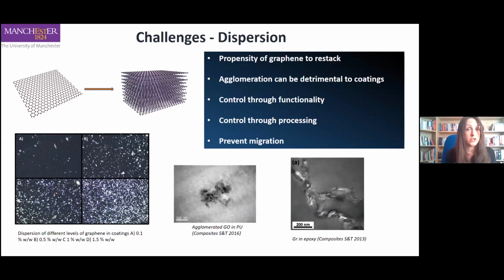So milling, high shear, dispersion, maybe the use of rheology modifiers to keep that graphene dispersed while your coating is curing. There's so many things you have to think about. The other thing you can do is to functionalize the graphene, and that can help with dispersion, especially if you're in sort of an organic polymer matrix. GO, for example, has all those oxygen groups and can help dispersion, and those functionalized groups can help prevent agglomeration as well. There's so many ways to modify graphene: silane, halogenation, nanoparticle grafting, grafting on polymers.